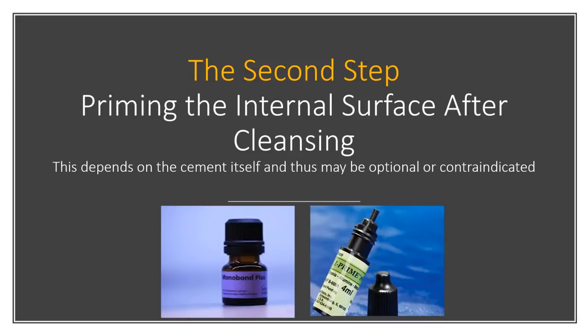In the Bisco family, they have a silane product, A and B, where you mix 2 drops each, and that's what I would be using to silanate Emax or a dilithium product. But for zirconia, let's say you're using a different cement and it says you need to prime it, then I would be using Z Prime. Ivoclar's Monobond Plus can prime zirconia and prime Emax and dilithiums.